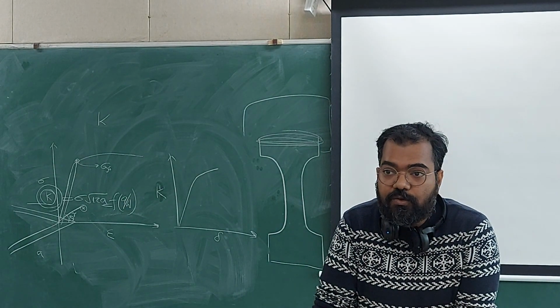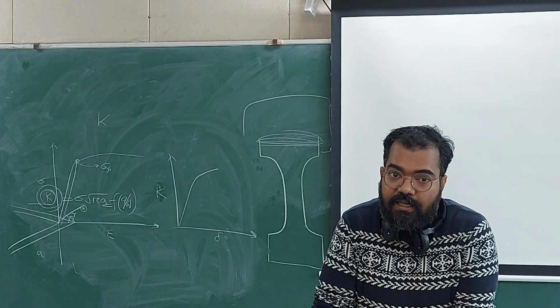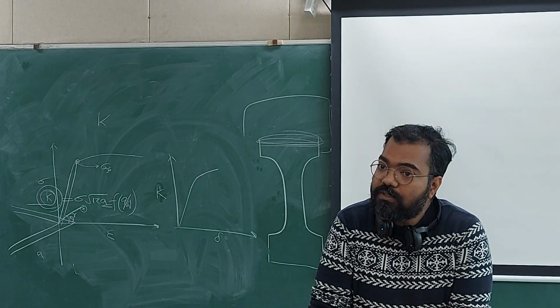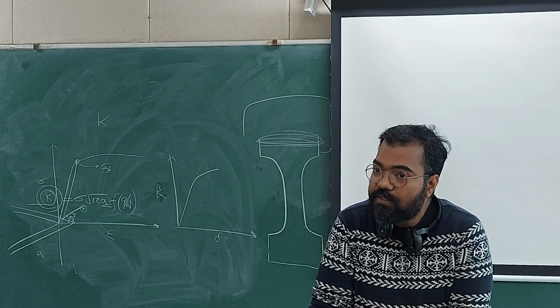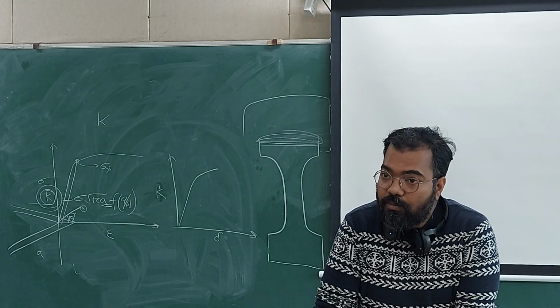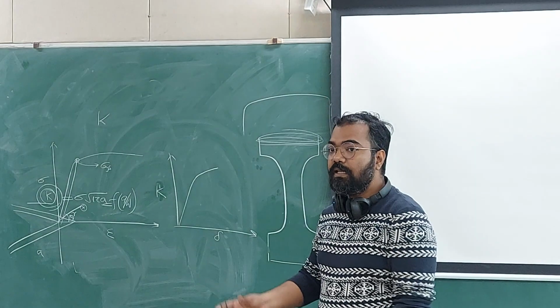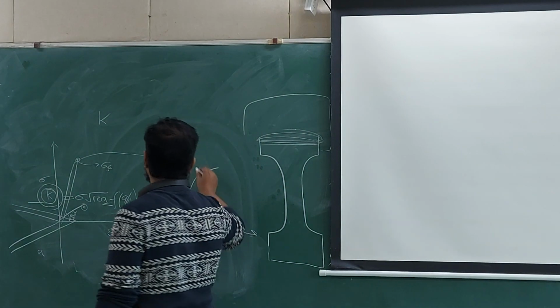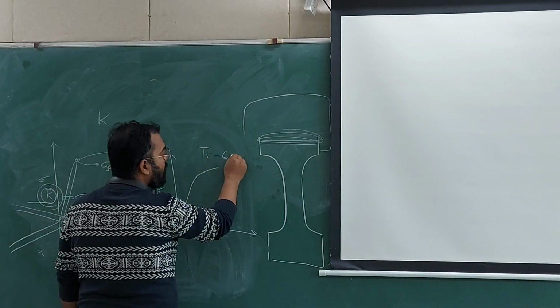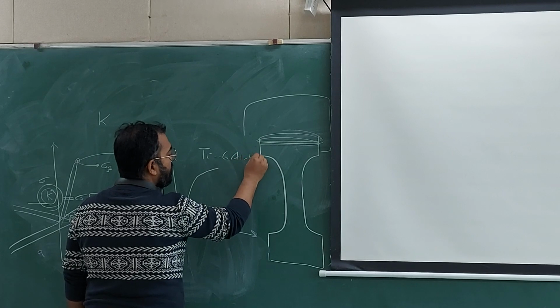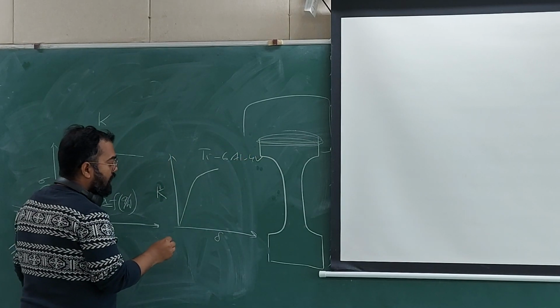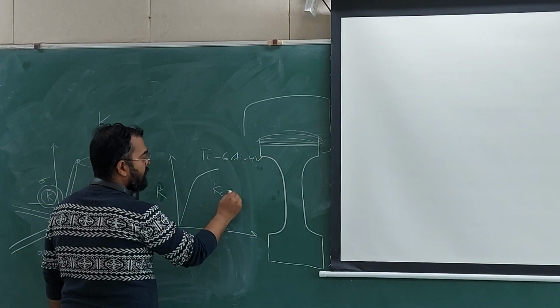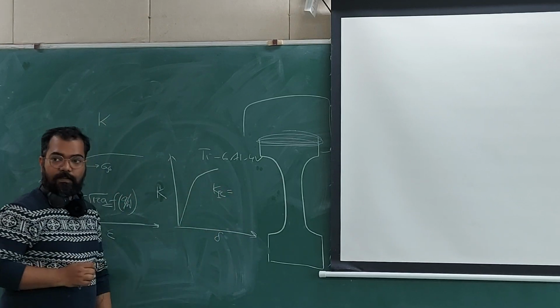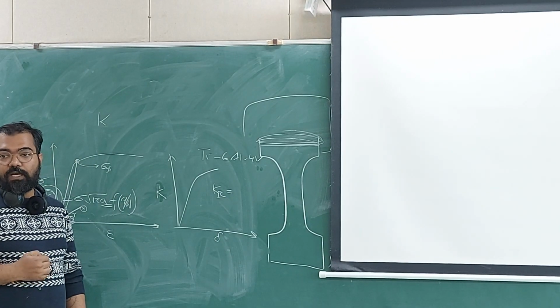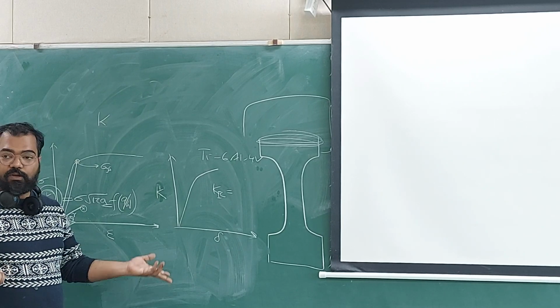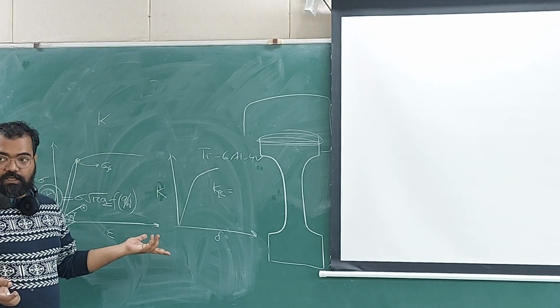So when you do mode 1 testing, you slowly increase the value of stress, and thereby you increase the value of stress intensity factor for the known amount of crack. Or you can know from the test that for, let's say, a titanium alloy, you are getting a critical value Kc, or K1c, I will call it, because I am doing the test in mode 1. If I just write Kc, I do not know in which mode the test was done.